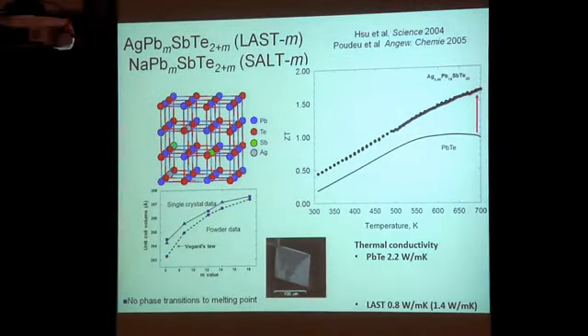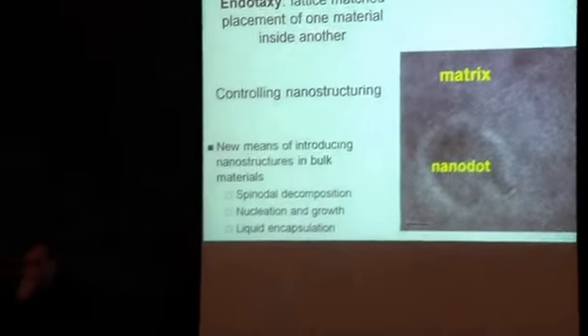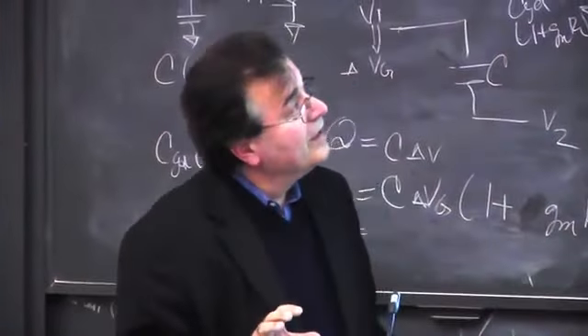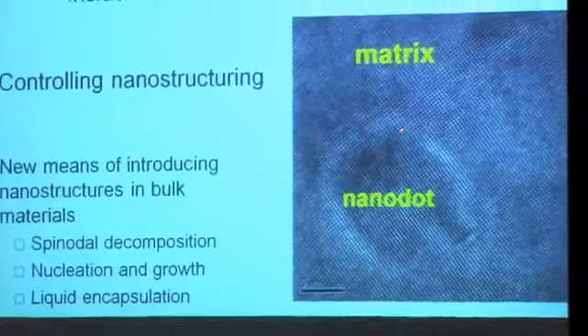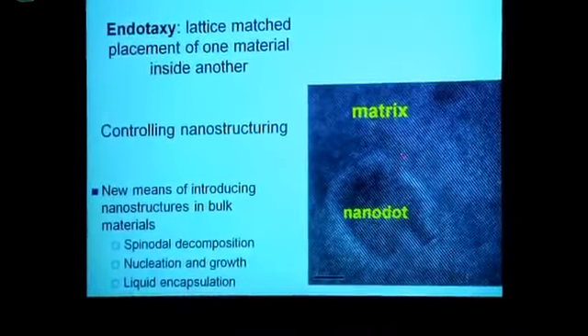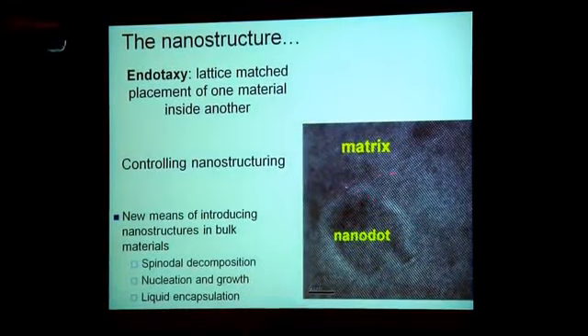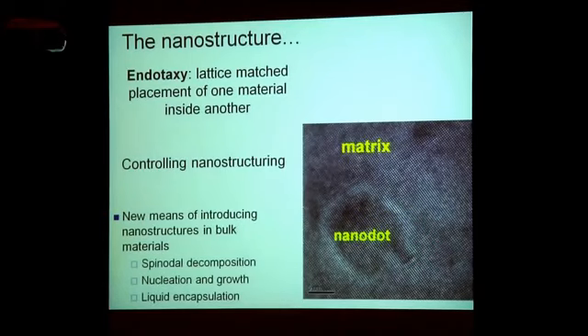That was intriguing. And so why was the thermal conductivity low? So we went into the guts of the material, looking at the atomic scale and the nanoscale using transmission electron microscopy, and we were surprised to find that this thing, even though it was following Vegard's law, was not homogeneous. It was inhomogeneous, and it had several other phases that had precipitated in the matrix. So we had nanodots precipitated in a matrix. They were quite coherent. And we thought that these things may be linked to the low thermal conductivity. We didn't know at the time.